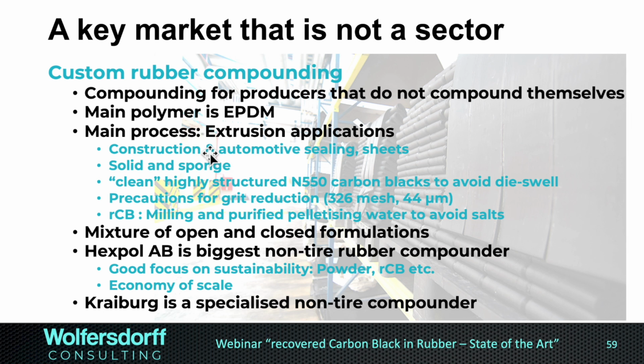Sheets, also extrusion. We might have solid or sponge. What is important to understand about the carbon black used here, it's a clean, highly structured N550 carbon black. So why highly structured? With a high structure, we can avoid a die swell, which is like blowing up the compound going out of the extrusion.